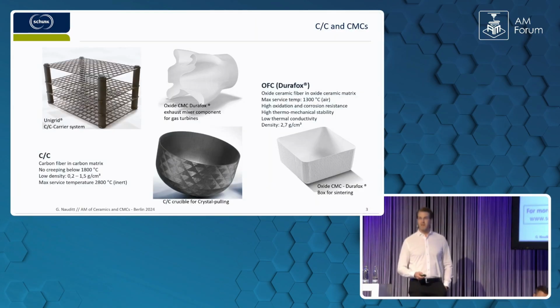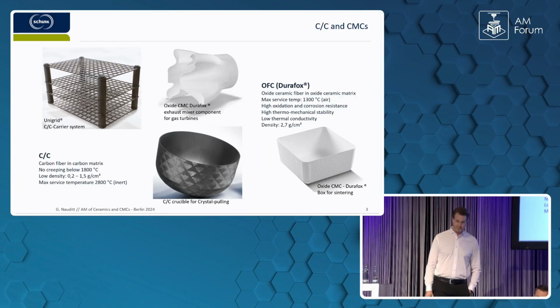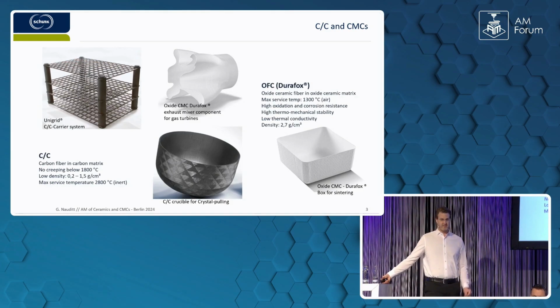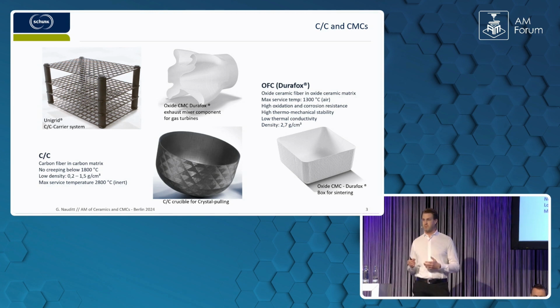I am working at the headquarters in Heuchelheim in Germany as an engineer for fiber reinforced materials, especially for CMCs. And we are producing them in Heuchelheim, like here shown, for example, the white ones. That's, as Fabia already showed us, an oxide fiber reinforced oxide ceramics. So we have an aluminum oxide fiber embedded in an aluminum oxide matrix. Or the gray or dark ones, that's a carbon fiber placed inside of a carbon matrix. And what's the beauty of this material?